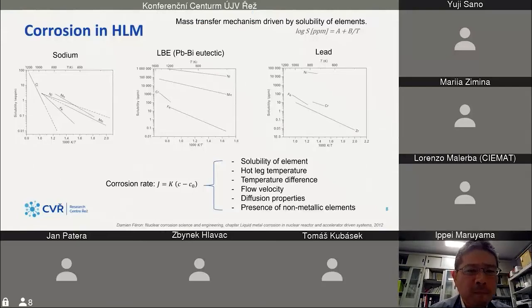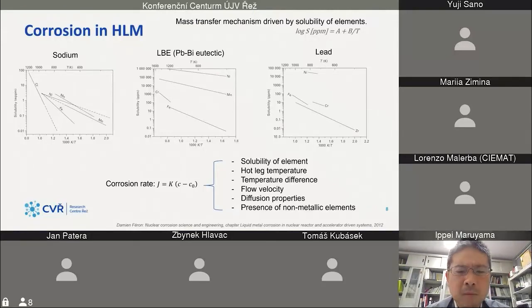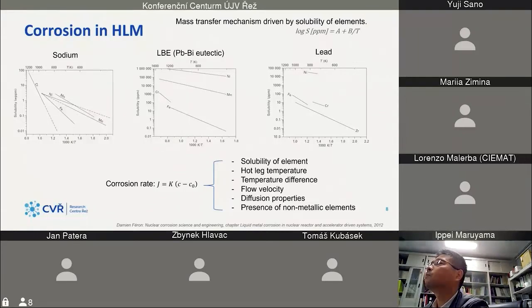The problem with corrosion is based on the solubility of elements, mainly nickel. As you can see here, for example, sodium is virtually non-corrosive for stainless steels because there is very low solubility of all alloying elements. But on the other hand, for heavy liquid metals it's a completely different picture, especially for lead-bismuth eutectic. That is highly corrosive, and we had to limit the temperature. And the situation with lead is 10 times better, I would say.